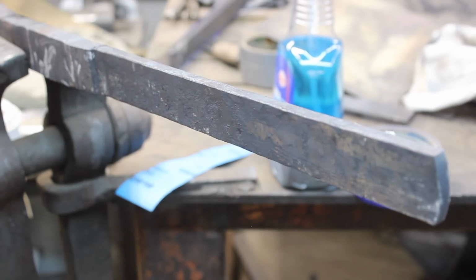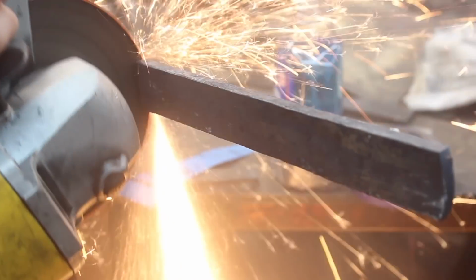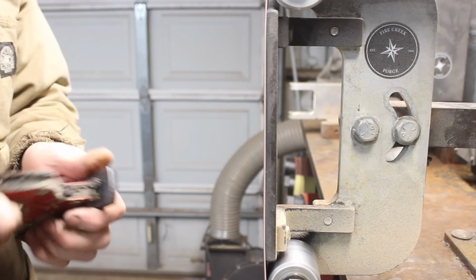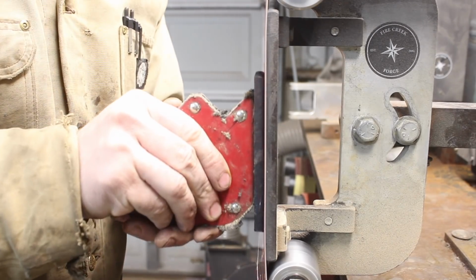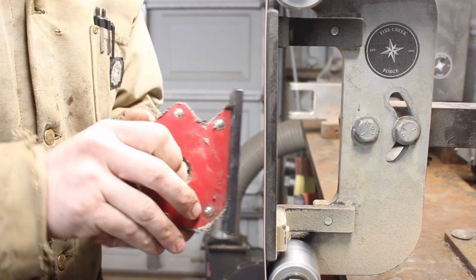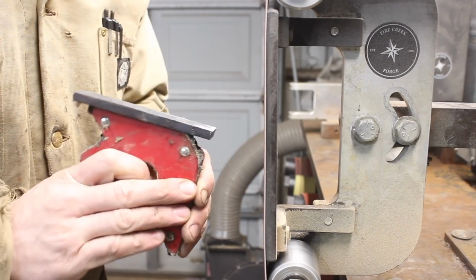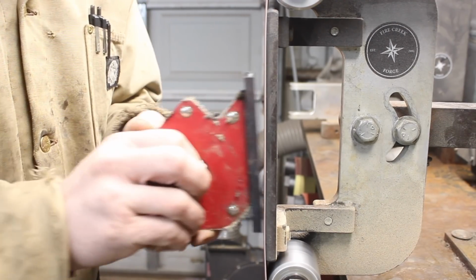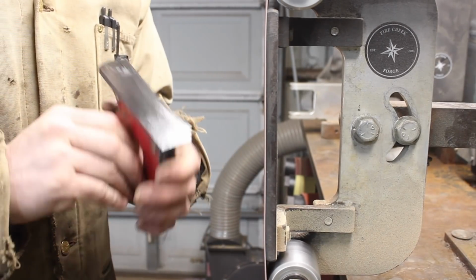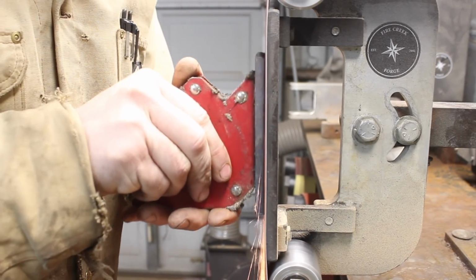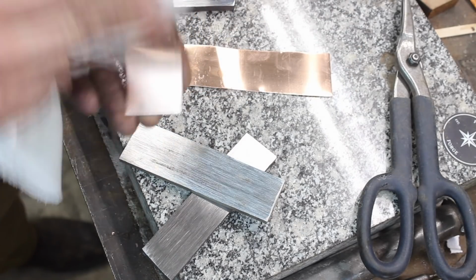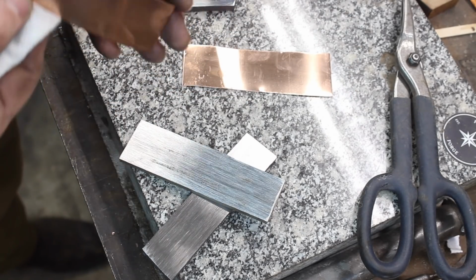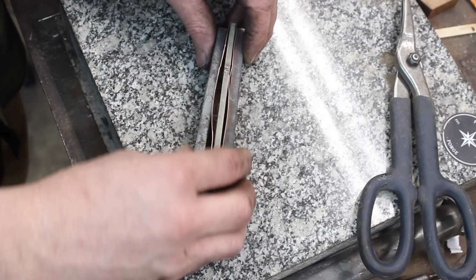So this is my pattern welded steel. We've got it drawn out, cut it off into 2 pieces, and then clean it up. So I've left it thicker than the center or edge steel for our billet, and that's because I need to grind off all this scale on the inside, and then on the final product, the same thing. We need to remove all of the scale and decarb so that we can etch and finish out the final surface and reveal that pattern. So just making sure everything is clean here.